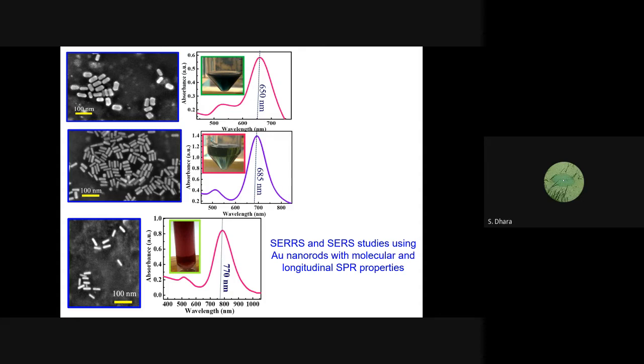Now, as you know, there are a large number of implications. When we talk about metal nanoparticles, particularly gold and silver, I'm not too particular about specific materials, but generally. Gold nanoparticles show the surface plasmon resonance as a single peak normally, but if it is an elongated structure, then you start getting another peak also. This gold nanoparticle peak is the first peak, around 500 nanometers, the signature peak of gold. But nevertheless, gold has an intraband contribution, which is what I was telling, that physics reached there.